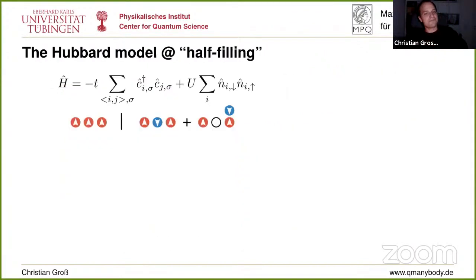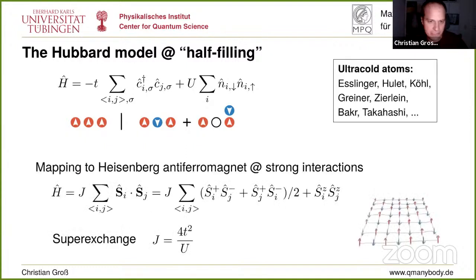Good. So let's start with the simple physics of the Hubbard model in 1D and at half filling. Half filling is what I explained: exactly the same number of fermions as sites, 1 atom per site. In this limit, at strong interactions, one can map the model to a Heisenberg antiferromagnet, as shown here. So we can map this complicated Hubbard model to a much simpler spin model.